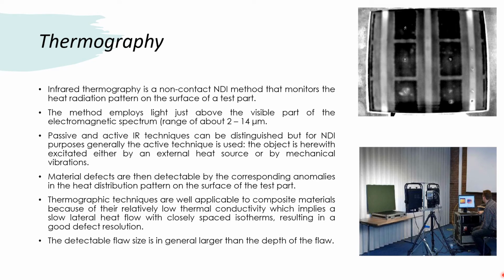Now coming to the thermography. Infrared thermography is a non-contact, non-destructive inspection method that monitors the heat radiation pattern on the surface of a test part. The method employs light just above the visible part of the electromagnetic spectrum, in the range of about 2 to 14 micrometer. Passive and active infrared techniques can be distinguished, but for non-destructive inspection purposes generally the active technique is used.